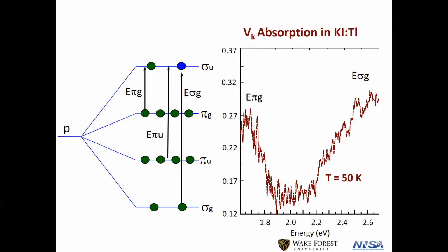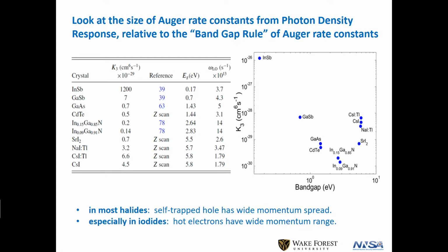But the point is, it happens very fast. We're still working on it, and we've written it into our next 3 years to do a better measurement. We're down to a 1 picosecond upper limit on the self-trapping time. That's not nearly well enough determined to have the effect we think it does. It needs to be way faster than that. Is there actual motion of the atoms when this happens? Yes, they relax together and just form a molecular bond. It's strong, and that's where they stick, because they're not going to move. It's no longer a band state at that point. You localized it.